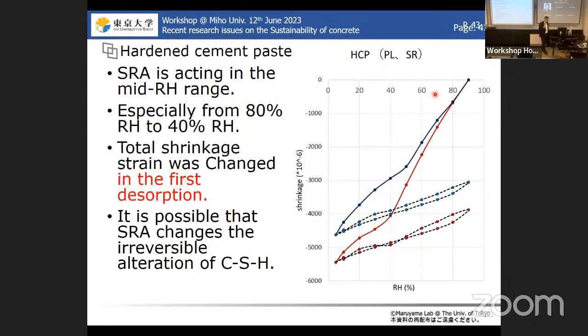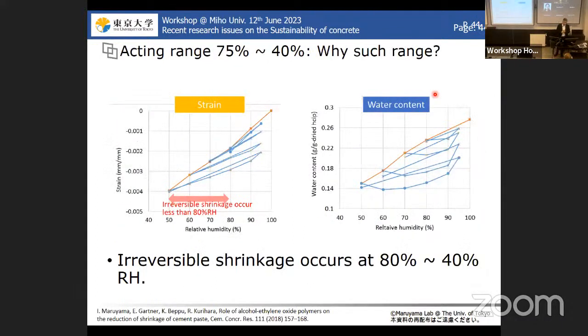So meaning that the shrinkage of the hardened cement paste mitigated by a SRA is only acting on a first desorption branch, and especially on the relative humidity range from 80% to 40%. And what is it? So I tried some additional experiments, putting the specimen in this, a first desorption branch, and this is water sorption, and this is a strain measurement.